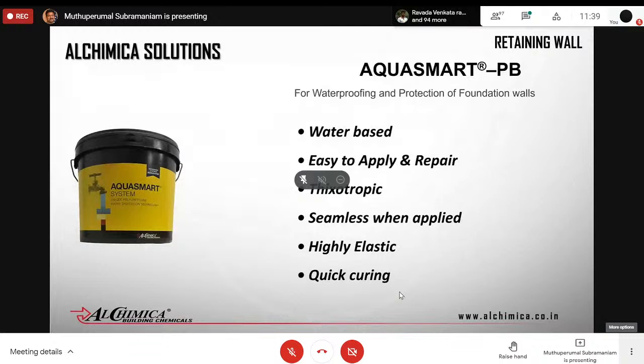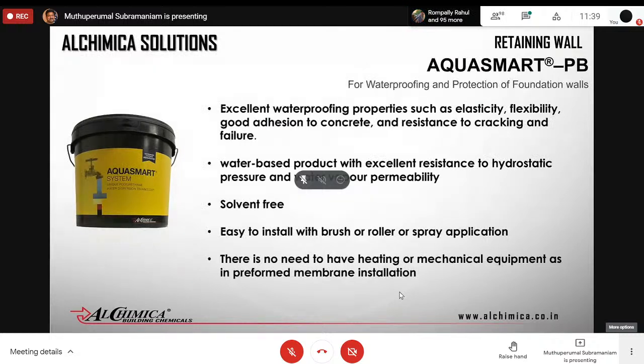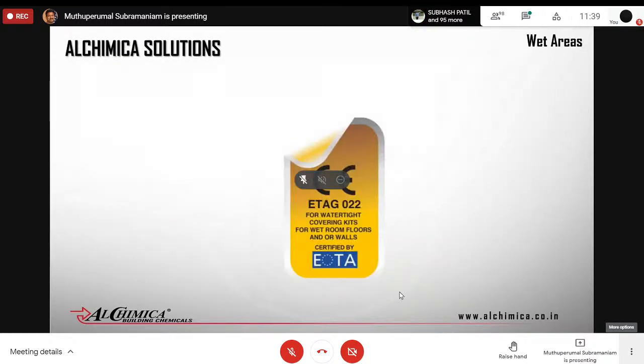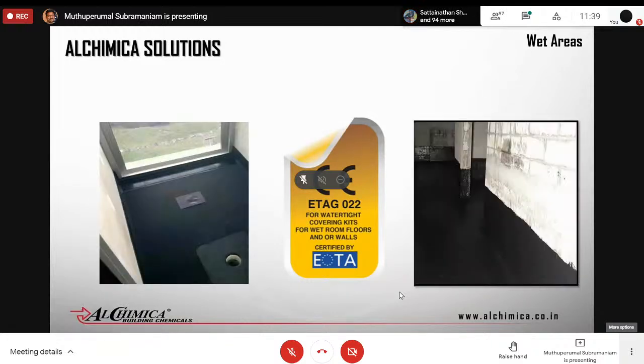When you apply it, suppose you want to do backfilling quickly, it dries within 3 to 4 hours, and then you provide a protection board and then backfill the soil. It is also solvent-free and highly elastic. It can be applied by brush or roller, and sometimes we can use spray if we have a large work front to be treated with waterproofing. This product is also CE certified on ETAG 022 for its performance standard. So this product can also be used inside toilets and balconies, because in a confined room, if I use a solvent-based coating, sometimes the solvent evaporates and creates suffocation to the applicators.